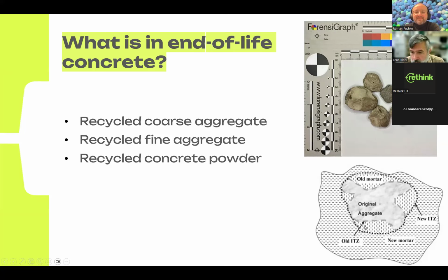Now, an important feature of concrete is what's known as the interfacial transition zone, this ITZ. And this interfacial transition zone is the point where the cement paste touches the aggregate. That's a point of weakness. In normal concrete, you just have this interface between the aggregates and the mortar. But in recycled aggregates, you have your original interfacial transition zone. You can have an interfacial transition zone between original aggregate and new mortar, or between adhered mortar and new mortar. And these ITZs are points of weakness. We need to know more about these if we're going to improve our understanding of end-of-life concrete.